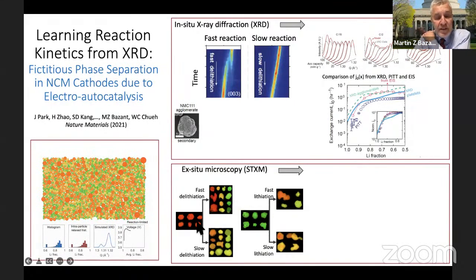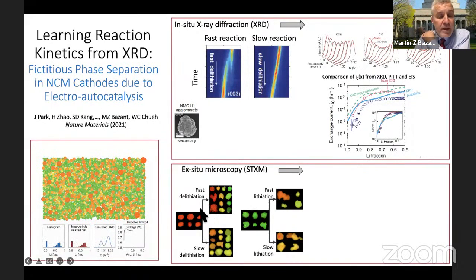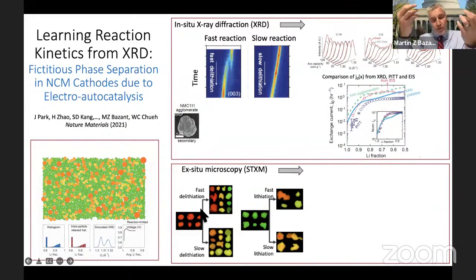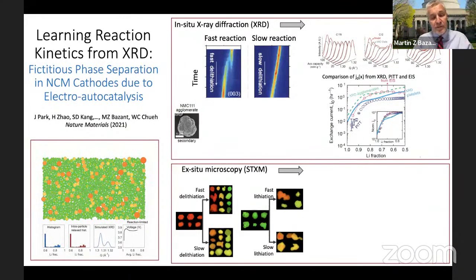And so the way to test that is simply to turn off the current. If you do it quickly, then the particles just relax to their equilibrium state. And so if it's diffusion, all the gradients inside the particle should go away, and you should find all the particles look exactly the same.